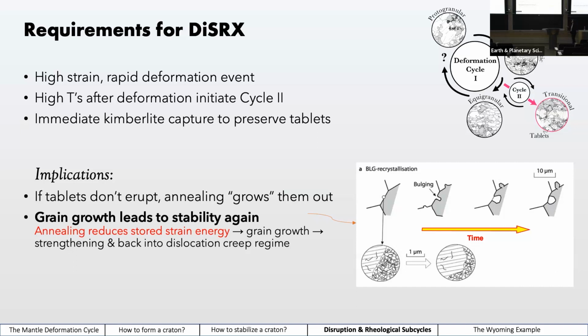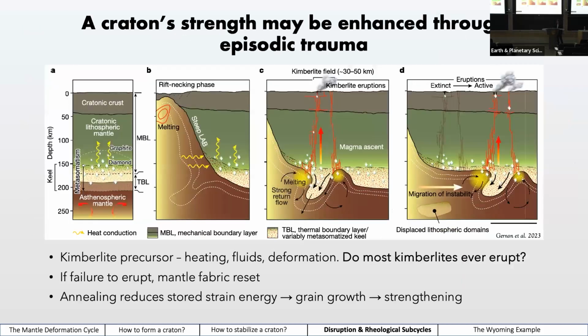So the implications are that if these tablet textured transitional xenoliths never erupt, the annealing process would grow those grains out. And that just leads to grain growth, which leads to stability. So annealing reduces the stored strain energy, leads to grain growth, and can strengthen the mantle back into dislocation creep, which makes it harder to deform again. So it's kind of like the kimberlite that fails to bring these up actually helps re-strengthen the mantle. That's one way to think of it.